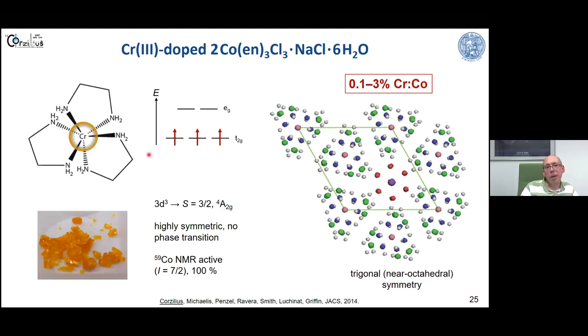This is a chromium complex, which is doped into a mixed crystal of cobalt trisethylenediamine trichloride in sodium chloride hexahydrate. In this case, chromium(III) has a 3d3 electronic structure, which gives a quartet spin and a 4A2g ground state, the symmetry-adapted term symbol. This shows that the three electrons occupy the three t2g orbitals of the d system with maximum multiplicity. So this gives us a non-degenerate ground state.